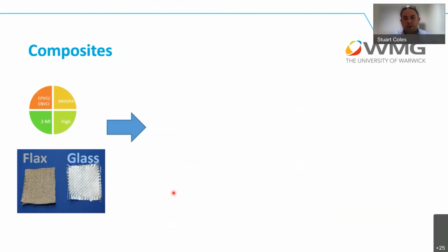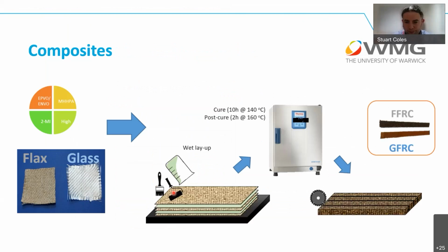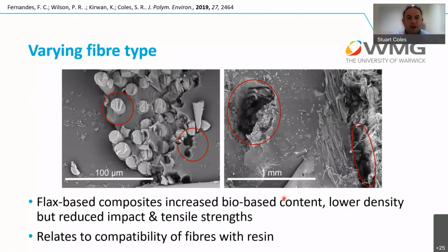So then we started looking at making composites out of these materials, and we wanted to see whether they were compatible with a variety of different types of fibers. Again, following a similar sort of curing system, we made a flax fiber reinforced material and a glass fiber reinforced material. Used our optimized polymer mix to see what sort of composite properties we were getting. And we found that